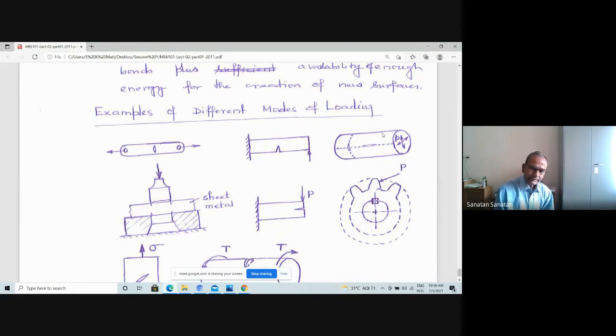That means if you consider this beam split into two segments about the center line, the top half and the bottom half, because of this loading those two halves are trying to shear over one another. So if you consider a glue joint at the center line, that glue line will be subjected to shear stress, and that crack will be extended by shear stresses along the center line. It is mode 2 loading on the component. So that's how it is, very important.